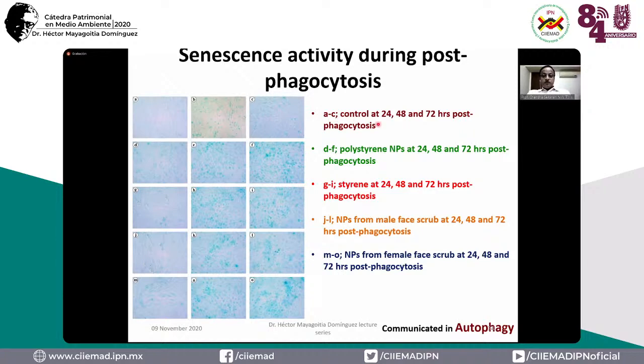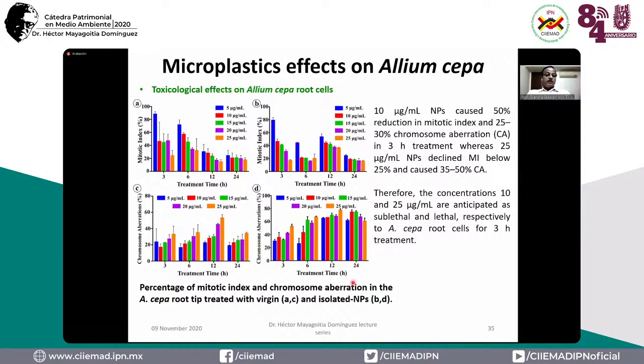And this, A to C, is the control at 24, 48, 72 hours post-phagocytosis. D to F is the polystyrene nanoparticle at 24, 48, 72 hours post-phagocytosis. G to I is the styrene; we took the monomer styrene at 24, 48, 72 hours. J to L is the nanoplastics from male scrub at 24, 48, 72 hours, and M to O is from the female face scrub. So we could see senescence activity, the aging of the cell, after post-phagocytosis due to nanopolystyrene or nanoplastics.